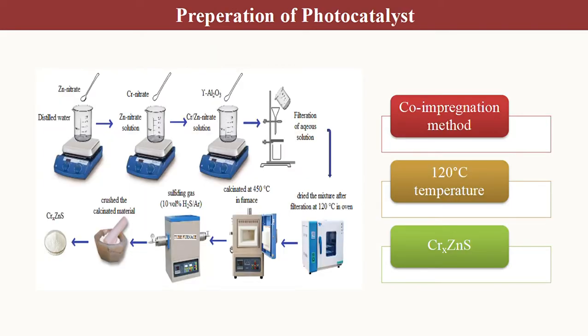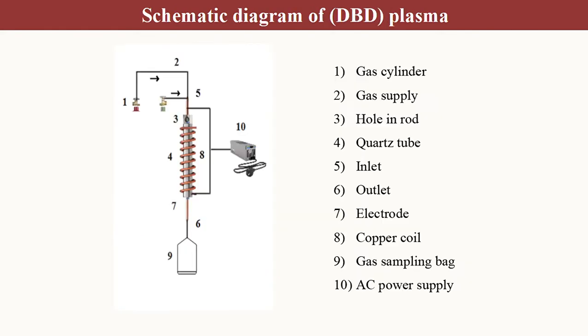Preparation of photocatalyst. The photocatalyst was prepared by the co-impregnation method by adding zinc nitrate, chromium nitrate, and aluminium oxide into distilled water with continuous stirring. The prepared solution was filtered and then dried at 120 degrees Celsius. The dried material was calcinated at 450 degrees Celsius while argon gas passed through the furnace tube. After the crushing process, a fine powder of catalyst was formed. This is a schematic diagram of the DBD setup used for hydrogen production by cracking hydrogen sulfide molecules over the composite catalyst.